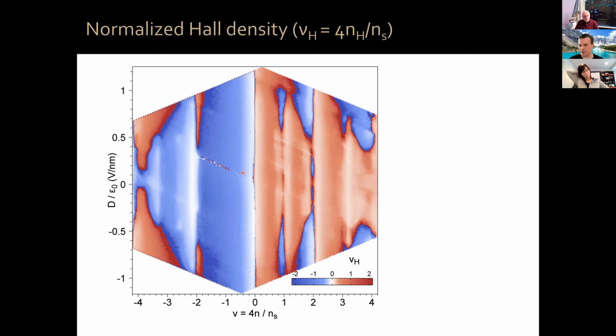Now to 0th order, most of the features that we see in this diagram can be associated with one of the following 3 situations. The first is a behavior which is characteristic of a Dirac point or a gap, where your normalized Hall density changes sign, crossing smoothly through 0. Remember at a gap or Dirac point, your carrier density changes sign smoothly and goes through 0. So your normalized Hall density does the same thing, goes smoothly through 0. This happens, for example, here at charge neutrality, where the Fermi energy goes through a Dirac point. You can see here that you go from dark blue to light blue to white, light red, and then darker red. Exactly the behavior that we see here.